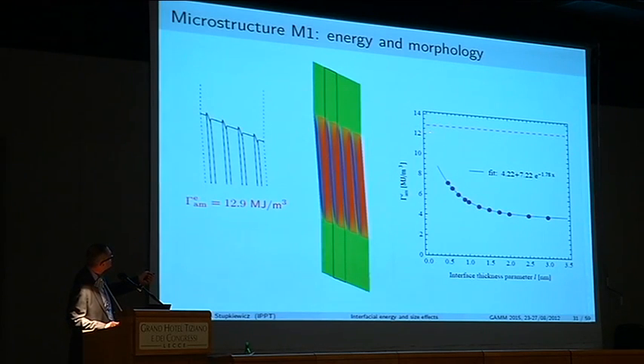So again, close. But what we see is that now the result of phase field modeling depends really strongly on the parameter, which is supposed to be just a numerical parameter. So one has to do something about it. We don't have a ready answer to this yet. Anyway, this is the result of this analysis.